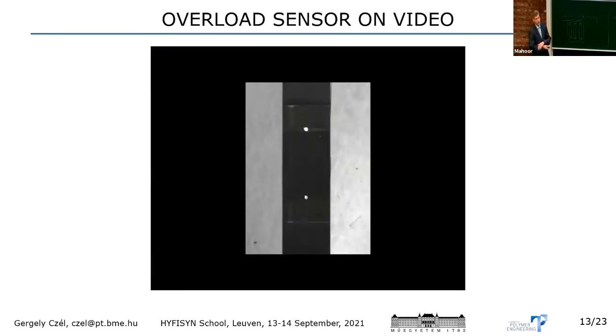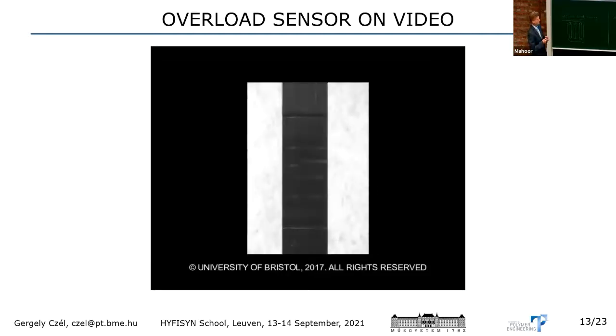And also we developed this concept, the hybrid composites, into an overload sensor, which was patented in the UK. So if we simply stick a piece of glass and carbon composite on a substrate and we put it under tensile load, according to the failure strain of the thin carbon layer, we can tell at which strain did we stop with loading the composite part. And this was again just something we discovered on the way when we wanted to develop pseudoductile fragmenting hybrid composites.